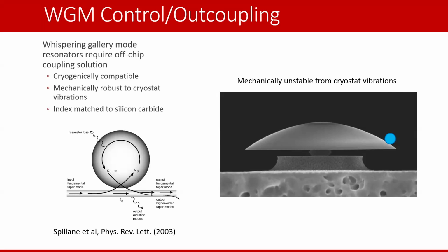But they did this with a tapered optical fiber. By taking an optical fiber and melting it and pulling it, they were able to cause the optical mode in the optical fiber to extend and then evanescently couple to their whispering gallery mode cavities.